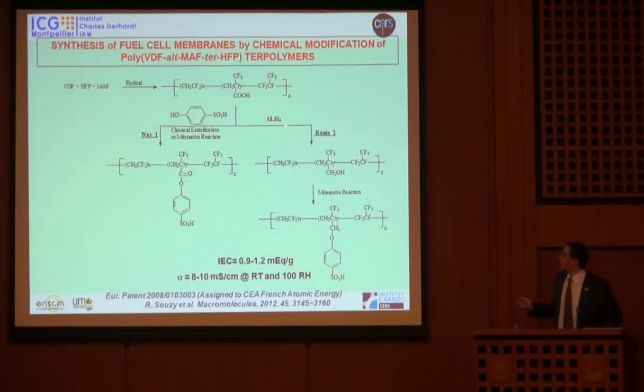Started from this polymer, we decided to make a reduction of the carboxylic acid in order to make a primary alcohol. And this is very interesting because in this case, by proton NMR, it was possible to confirm the content of MAF in the system. Okay? Because in proton NMR, we have, of course, some overlapping of the two protons arising from MAF and VDF. And then these primary alcohols are very reactive with phenol under Mitsunobu reactions. Okay? And if you react with phenol sulfonic acid, you can graft on your primary alcohol some aryl sulfonic acid. And this was the strategy we used.